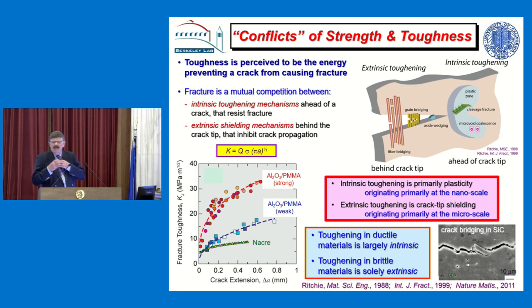I always liken that to if I was talking to you and I put a toffee in your mouth, it'd be more difficult to open and close your mouth. So that's the most important mechanism. There are wedging mechanisms as well. That's like a donut in your mouth, but that's more associated with fatigue. And deflecting the crack: if you can deflect the crack off the plane of maximum tensile stresses, you can induce toughening. So these are the mechanisms that primarily are associated with brittle materials.